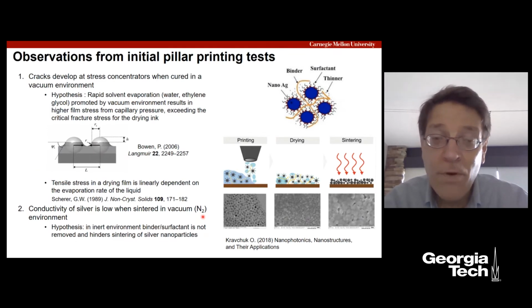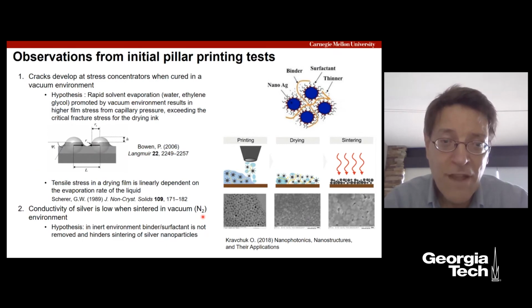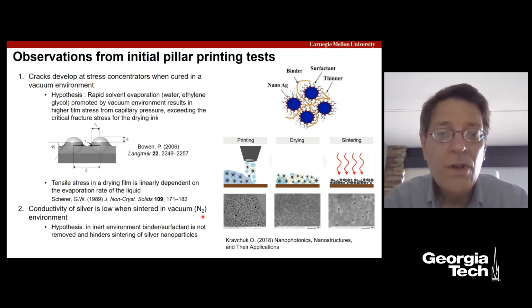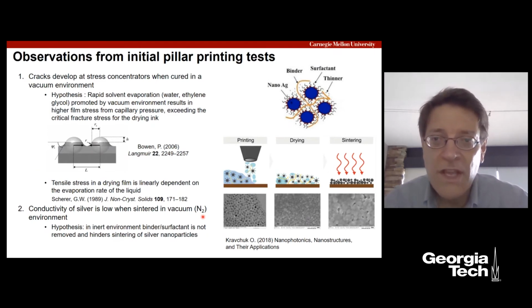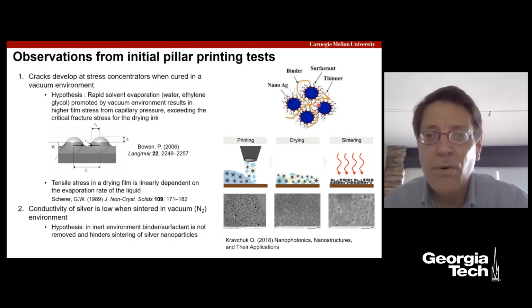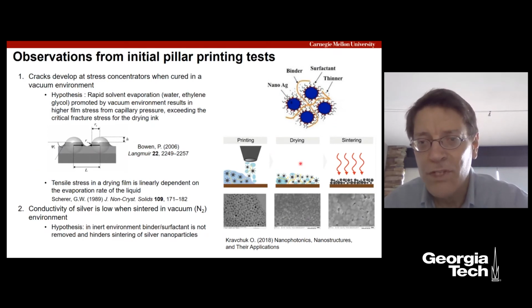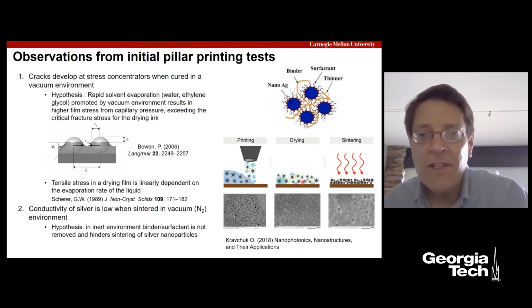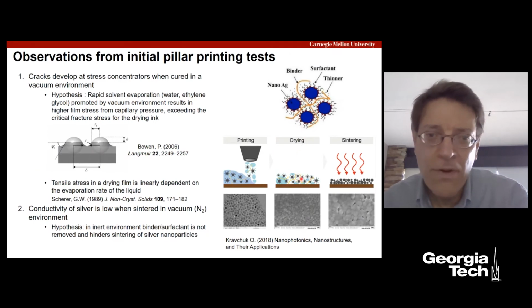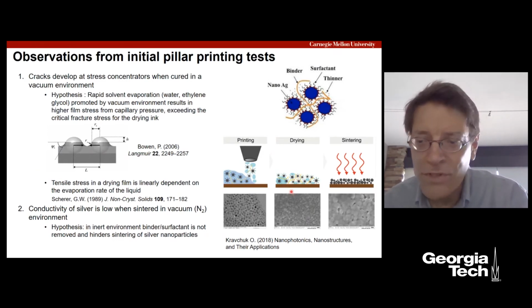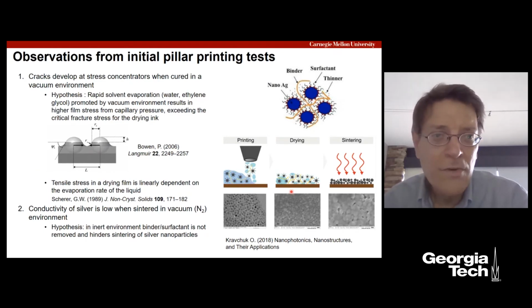And remember, we need to put the samples in a vacuum nitrogen environment because of the PDMS, so we don't really have a choice there. The issue is that for the sintering step, it's important to remove all the surfactant, or as much as possible, from the nanoparticles in order to get proper sintering. And oxygen plays a key role in effectively burning off, or evaporating, the surfactant at those temperatures. So we had a conundrum there of what to do.